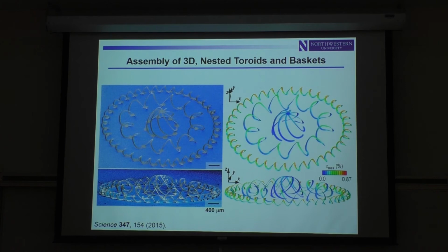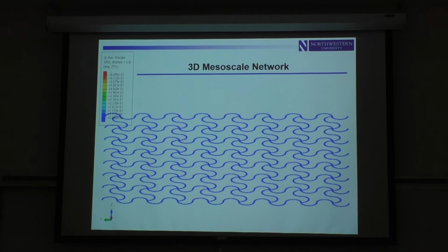And this works in silicon. It's a brittle material, but if you do the design up front, you can avoid any kind of bending strains that would lead to fracture. So you can do this without defects, as illustrated here. That's the modeling, a very, very good quantitative match. Now, if you think about biology, maybe some kind of interconnected mesh, maybe a deterministic design, maybe not.